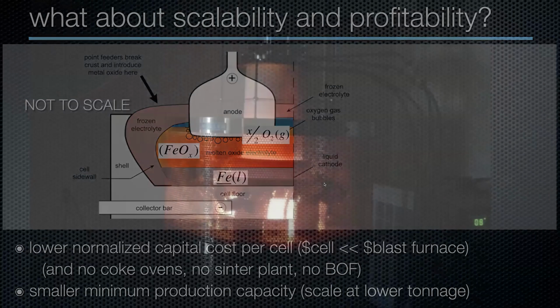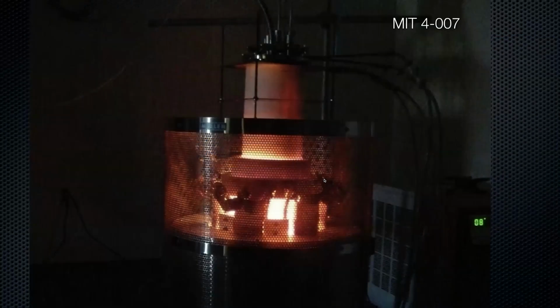So this is some work I was doing in the basement of building 4 at MIT. This is about 15 centimeters across, and this is an alumina tube. You can see at the top a fixture with electrodes and thermocouple, various leads coming out. And down here, just in the dark area at the bottom, is where the molybdenum disilicide windings are. It's glowing there at about 1600 degrees Celsius, and some of that light is radiating up the aluminum oxide tube.